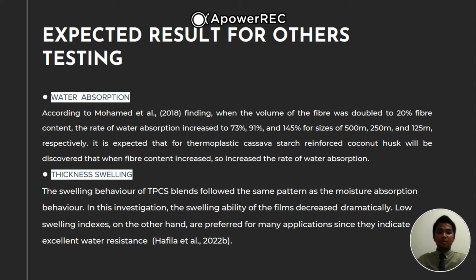For water absorption, according to Mohamed et al., 2018, when the volume of the fiber was doubled to 20% fiber content, the rate of water absorption increased respectively. It is expected that for thermoplastic cassava starch reinforced with coconut husk, it will be discovered that when fiber content increases, the rate of water absorption increases. For thickness swelling, the swelling behavior of the TPCS blend followed the same pattern as the moisture absorption behavior. In this investigation, the swelling ability of the film decreased dramatically. Low swelling indices, on the other hand, are preferred for many applications since they indicate excellent water resistance.